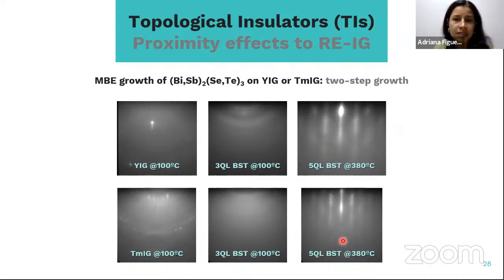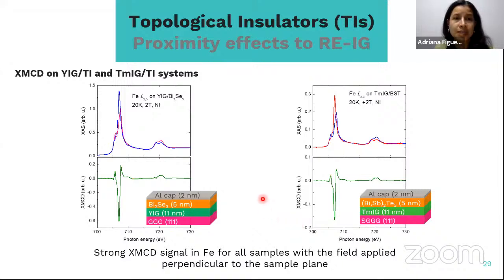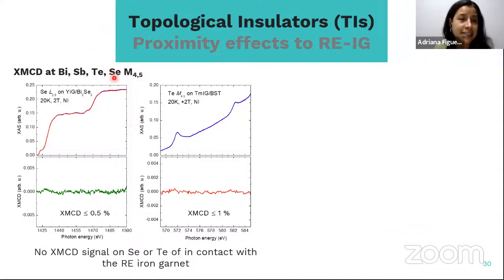And then we grow these stacks, and then we take them to the synchrotron to perform XMCD. So here I'm showing results at the iron edges performed on both YIG interfaced with bismuth selenide, and in this case thulium iron garnet, what we call TIG, on BST. And I'm showing here that we have a very strong XMCD signal on the iron atoms for all samples, all with the field applied perpendicular to the sample plane, which is what we are interested in measuring also. And then the next thing that we did was to tune the energy to the non-magnetic atoms again. And in this case, we also observed no XMCD signal on these atoms from the TI. So here I'm showing, for example, for selenium, what we saw for selenium on the YIG interface with bismuth selenide.